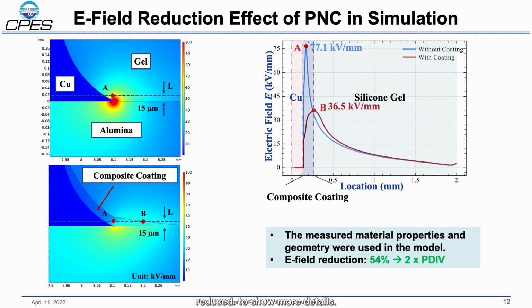And to show more details, we can extract the E-field from this measure line, and you can see the plot here. The blue curve shows the E-field along the measure line L without coating, and the red one shows it with the coating. We can see that the highest electric field was reduced from 77.1 kilovolt per millimeter to 36.5 kilovolt per millimeter. The measured material properties and the geometry were used in this model, and we found the E-field reduction is about 54%, which matches the PDIV improvement we observed in the experiments.